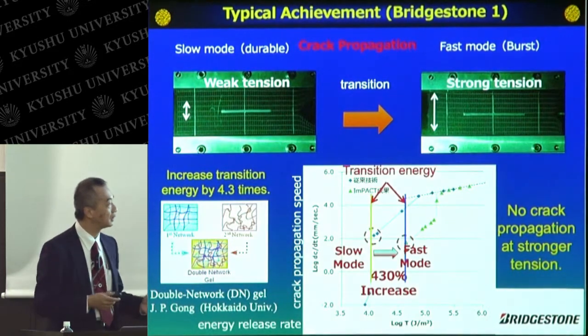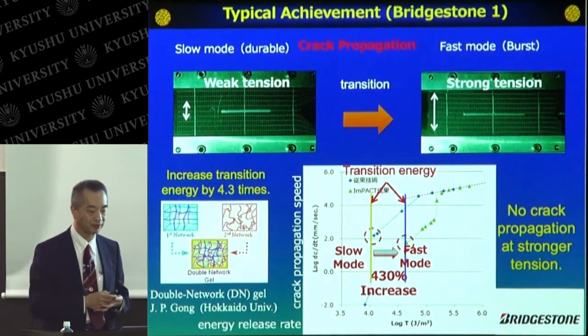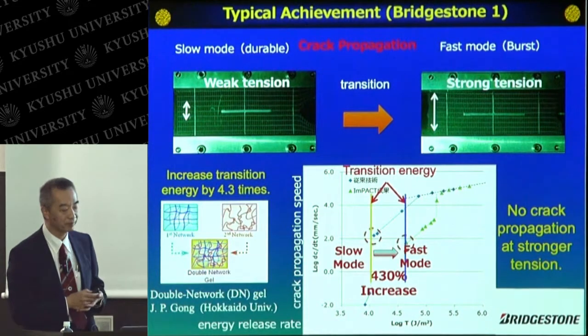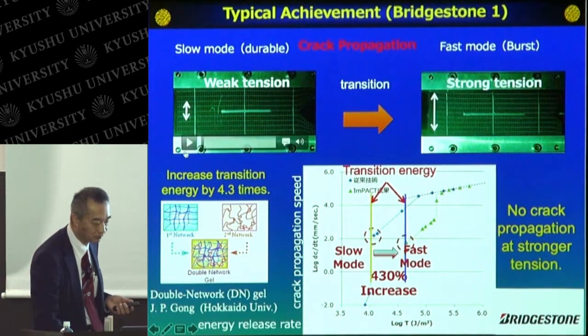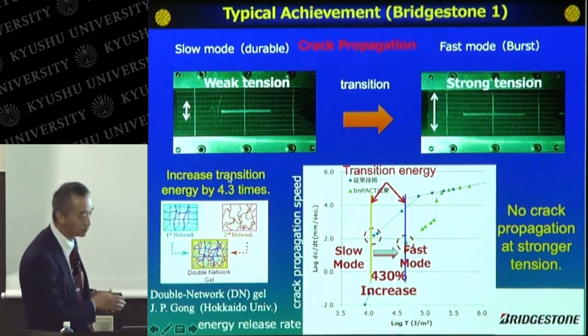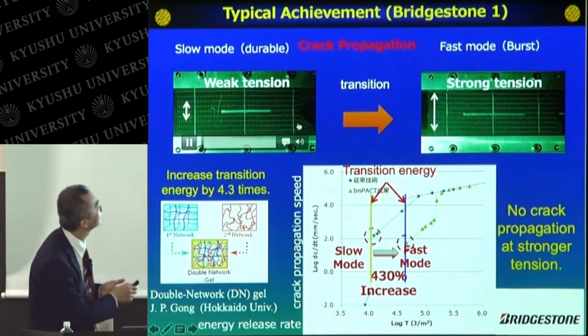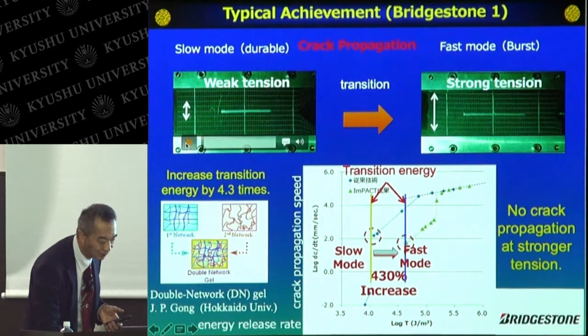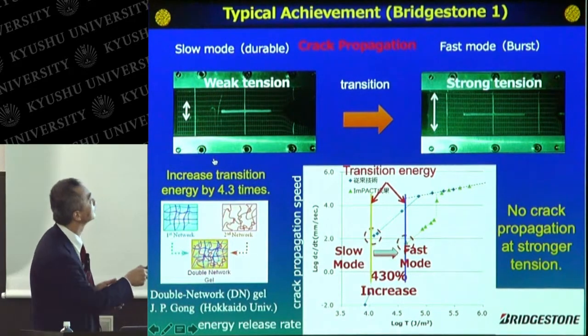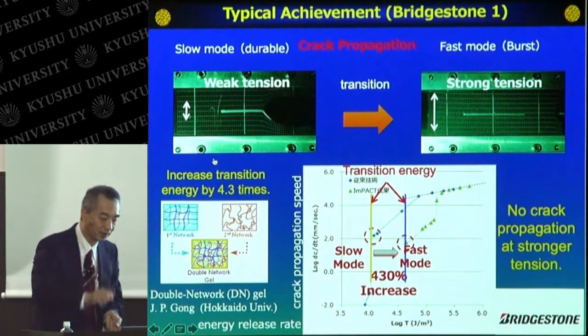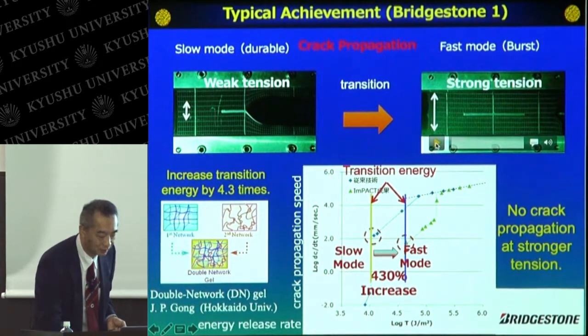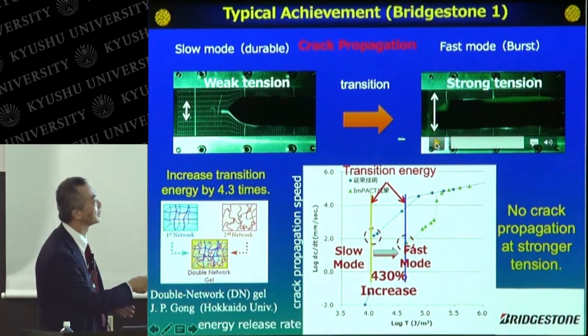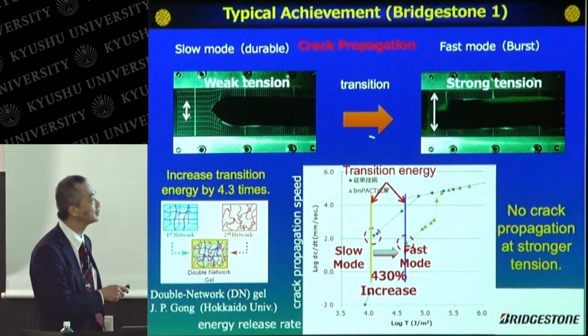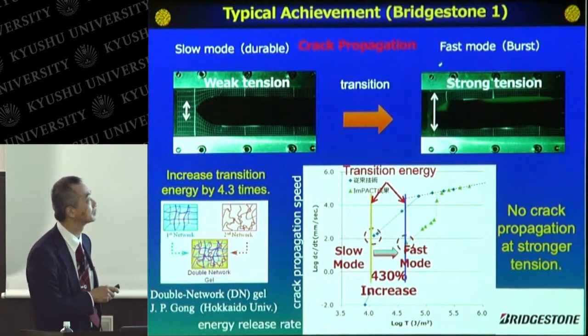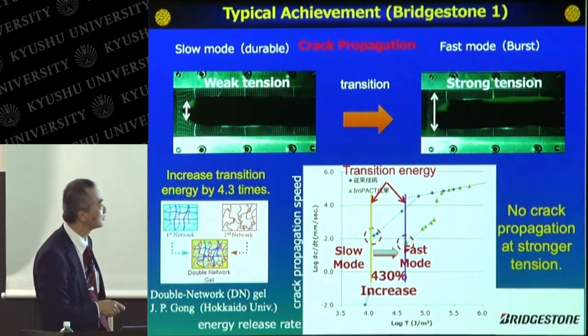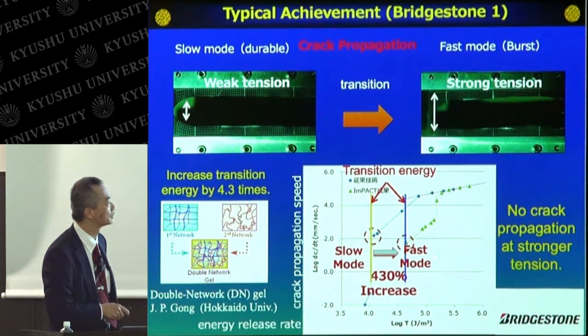Now let me show you the next achievement from Bridgestone. They focus on crack propagation. So when the rubber is stretched very weakly, the crack propagates very slowly, like this. Okay. But when you stretch the rubber more strongly, then the crack propagates very fast. The speed is increased about 10,000 times. This is called the crack propagation transition. So there is some threshold between the slow mode and the fast mode.